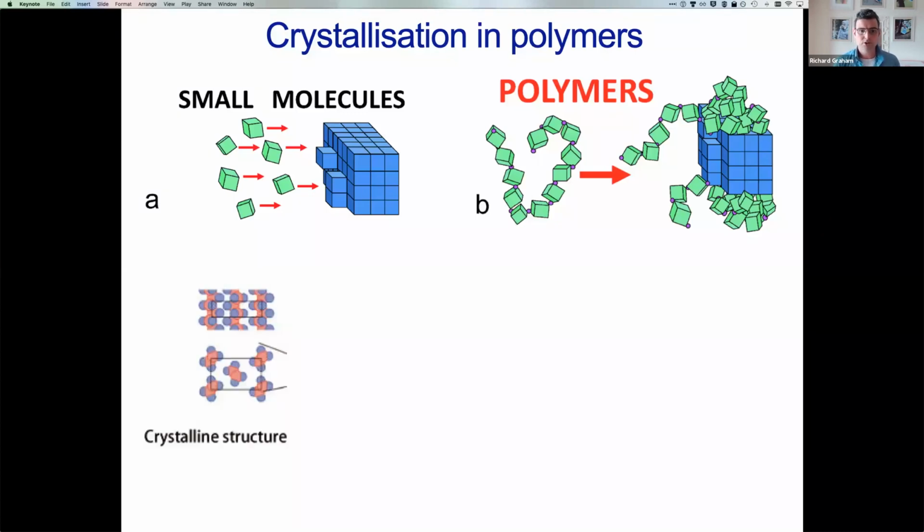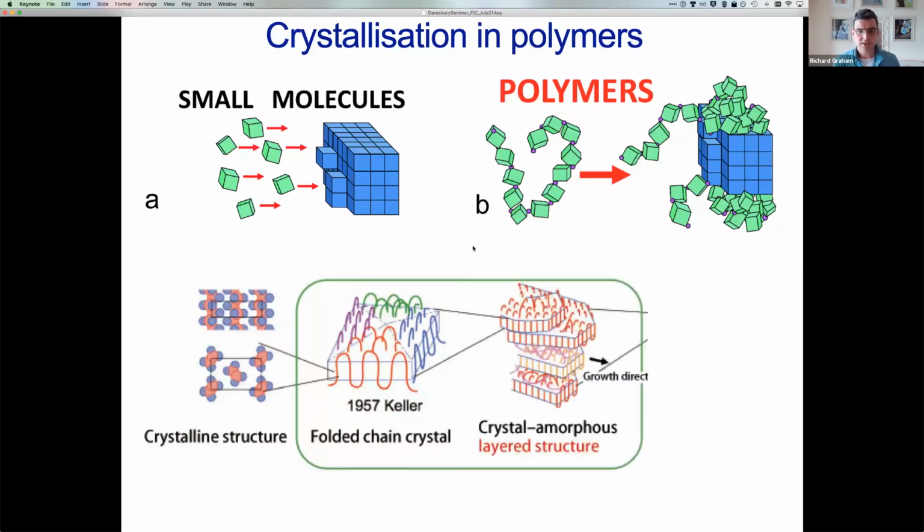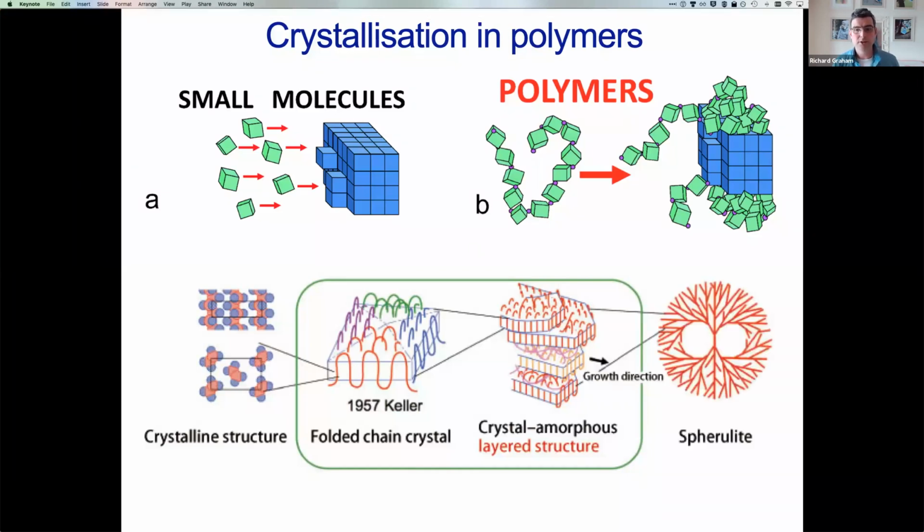They have this sort of local structure, then they form these sheet-like structures, where these loops that you can see here are the dangling ends. Those sheets then form layers of sheets and ultimately grow to form these spherulitic structures. So there's something really interesting going on, which is that the start of the crystallization happens down at this length scale here, but the point at which they're detected by experiments is up here. So there's this gulf between where the key initial processes are happening and the point at which the experiments start to see the result of that process.